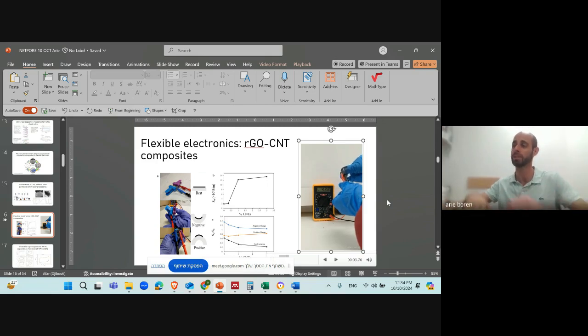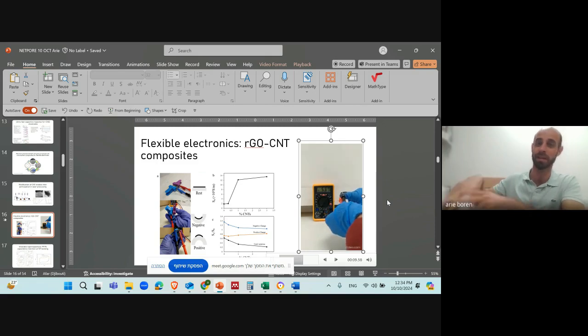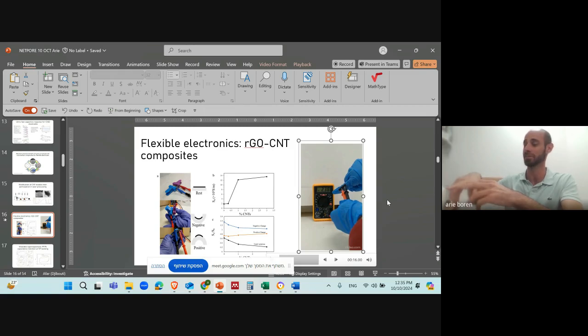So what we did here is we directly printed this graphene on a nitrile glove. I told you we can do it on any substrate. And when it is bent, my student Ashmita's finger bending her finger, you saw that the conductivity didn't change much. We can bend it negatively and positively, and you see that the change is not very significant. So we can keep that conductivity even on a flexible substrate. And this is achieved with the laser.